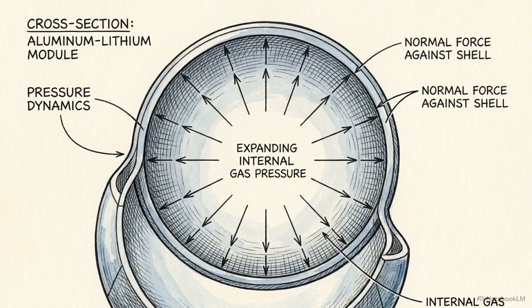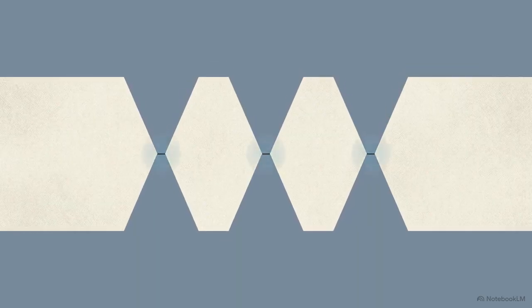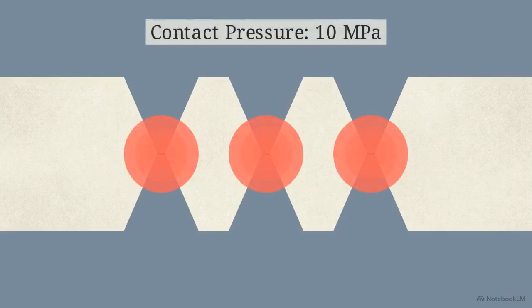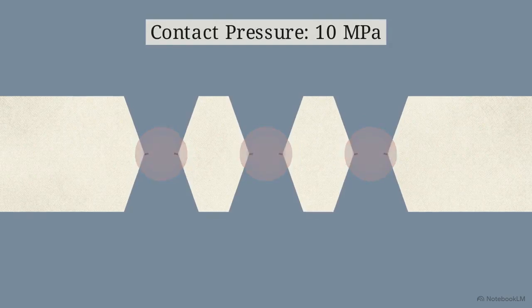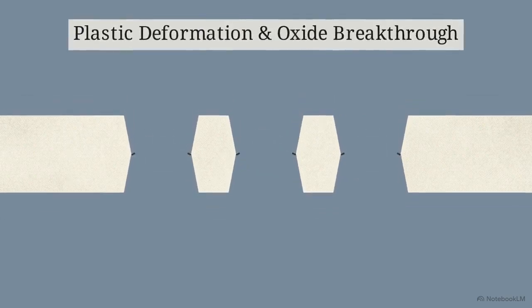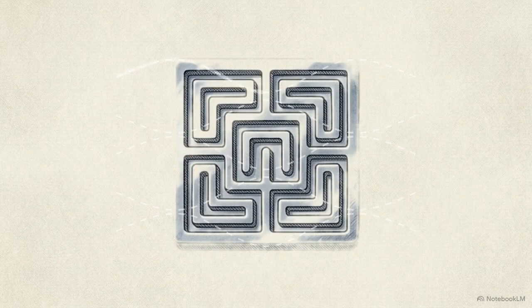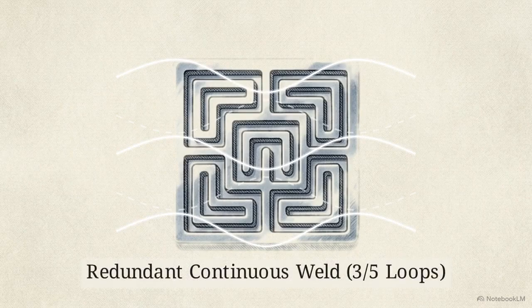Elevating the internal pressure to 0.1 megapascals, about 1 Earth atmosphere, generates roughly 1,000 newtons of normal force on each patch. The load concentrates exclusively on the ridge tips, spiking contact pressures to 10 megapascals. This induces plastic deformation. As the metal crushes together, breaking through native oxide films, 3 of the 5 topological loops close, forming a redundant, continuous weld.